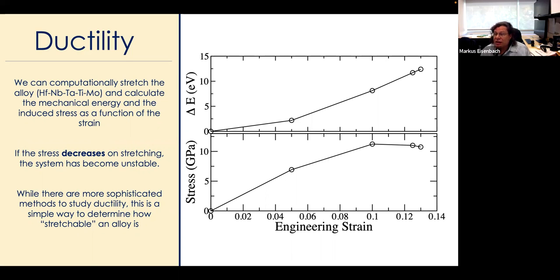Right. So to actually look at timescales at which this reordering of atoms happens, you'll have to go beyond just molecular dynamics, where you solve Newton's equations for the movement of the atoms, and actually add thermal excitations, or the probability of this, using something like a kinetic Monte Carlo, where you say there is a certain barrier height in the energy landscape that you have to overcome for atoms to move to new lattice positions, and then you associate a time scale with this movement, and that then allows you to do simulations that go to actual time scales where you see this reordering of atoms actually occurring.